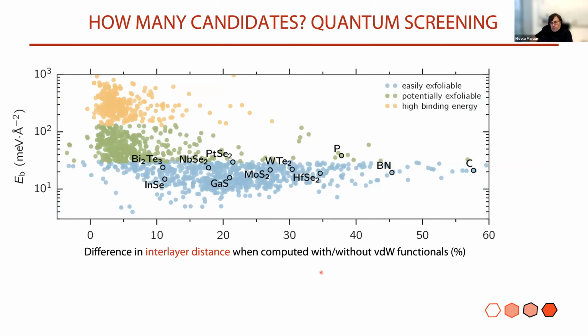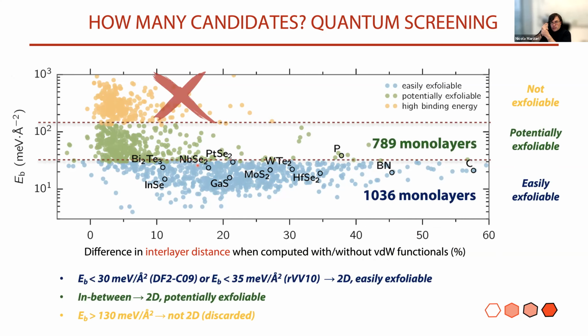All points are one of these 5,600 materials, and we plot these materials according to the binding energy of the layers. So this is graphite, low binding energy for one monolayer, and the structure of graphite is very strongly driven by van der Waals interactions. So you see, if you put all the materials that we have, we roughly cluster them around 3 groups. The blue groups of materials are mostly van der Waals bound with very low binding energy, we call them easily exfoliable. And we find not only graphite or boron nitride, but transition metal dichalcogenides, black phosphorus, and so on.